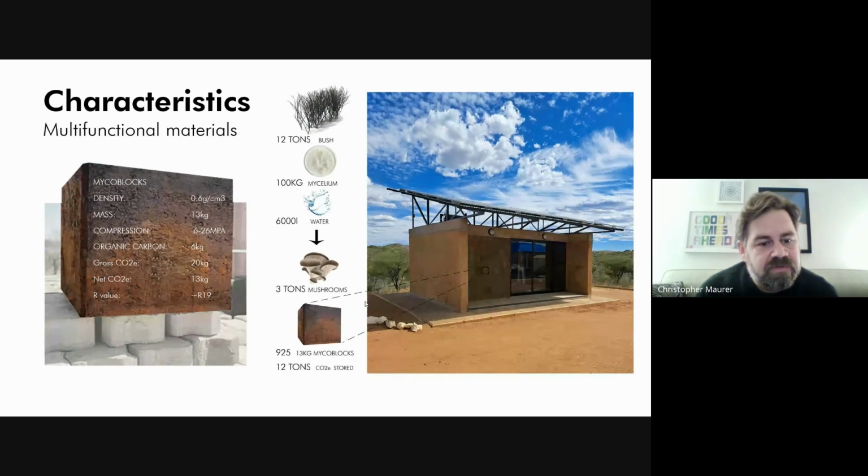This went through proper accounting and looked at double counting, which, as Jan mentioned earlier, is a major problem with carbon accounting, that sometimes people will count things twice. We were very clear, and we worked with a group at MIT to develop the criteria on that. And then R value, I'm not sure if that's used in Southern Africa, but that's what we use here in the States to talk about thermal resistance. For these blocks, we get about an R19, which is what I would need in Cleveland, Ohio, to insulate a building from our very, very cold winters, which we're experiencing right now.